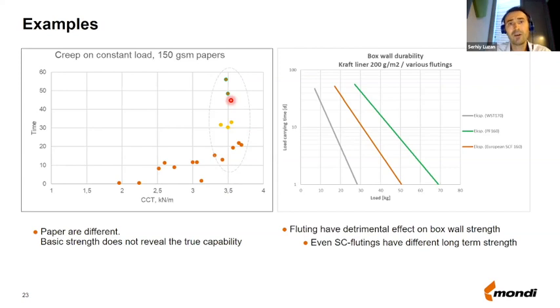So far I was telling you about the tests done for papers, but obviously the same tests can also be replicated for corrugated board and also for boxes. So here, for instance, you have an example already of the corrugated board. You have 3 lines which represent the resistance of corrugated board to load at constant load. And this line represents the corrugated board made with 2 times kraftliner 200 GSM and 1 time recycled medium 170 GSM. And these 2 lines show you the corrugated board which is made using 2 times semi-chemical fluting in 160 GSM.